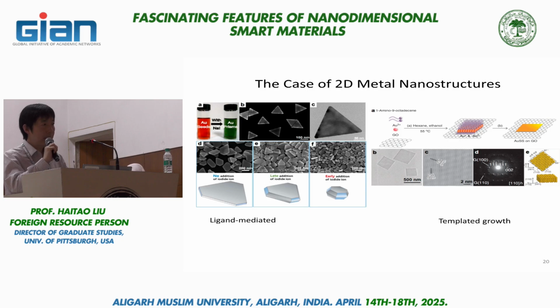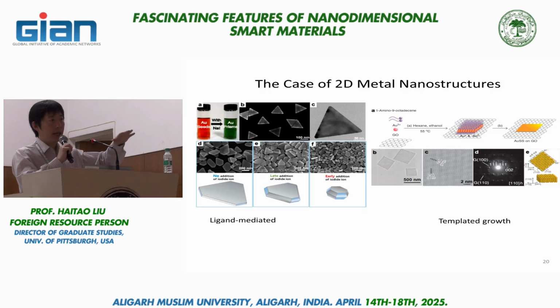There's also templated growth, where you start with some kind of a 2D template. In this case, it's graphene oxide. It's a surface that has a lot of hydrophilic oxygenated groups that can adsorb and attach to metal clusters or metal atoms. From here, if you add gold precursor and if your conditions are right, you can get 2D gold plates. And if you look at the B panel, that is a TEM image of square-shaped metallic 2D sheets.